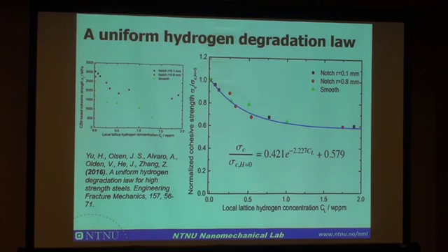This is the local lattice hydrogen. Here I have to mention that this is the first stage. We have not considered the trapped hydrogen. This is only lattice hydrogen. And we plot these results for different specimens: the smooth specimen, the notched radius 0.1, radius 0.8. And it looks disordered. However, if we normalize the cohesive stresses with hydrogen and without hydrogen, we got a very nice fit. And this is called the uniform hydrogen degradation law. We have just published this in the beginning of this year.